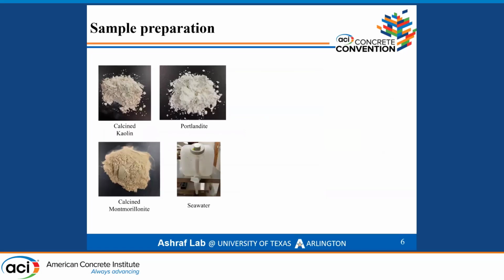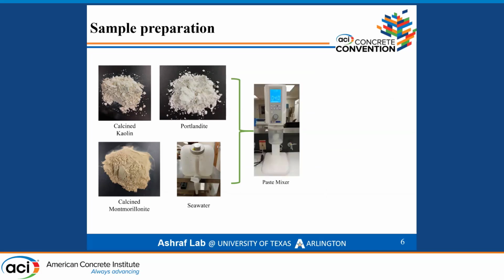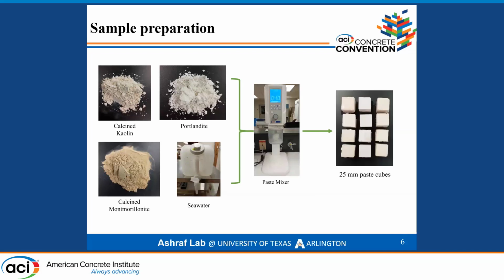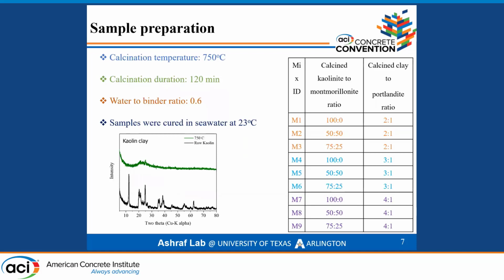For sample preparation, we took two types of clay, calcined kaolin and calcined montmorillonite, and we mixed them with Portlandite and artificial seawater. Then we mixed in a paste mixer and prepared 25 millimeter paste cubes. For this, we used a calcination temperature of 750 degrees Celsius, as you can see in the